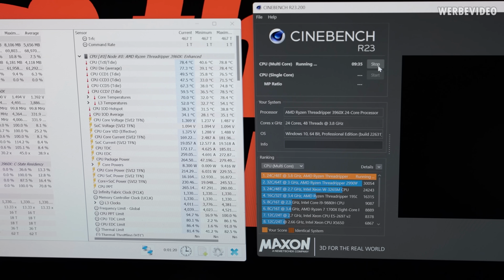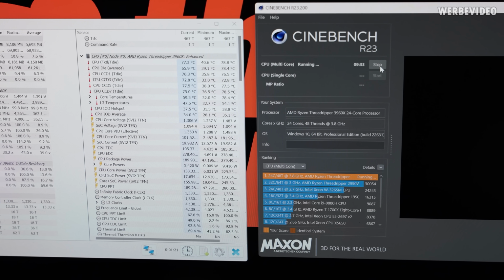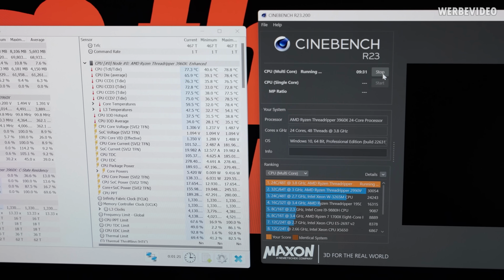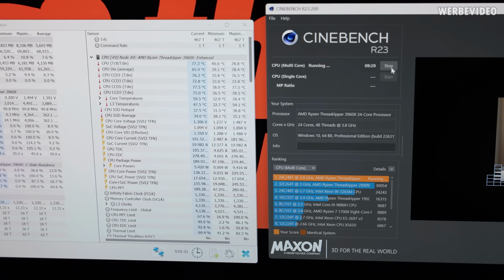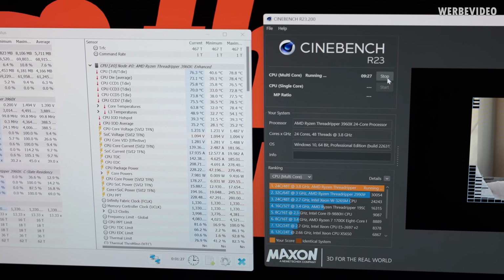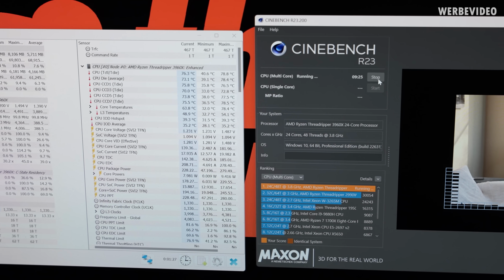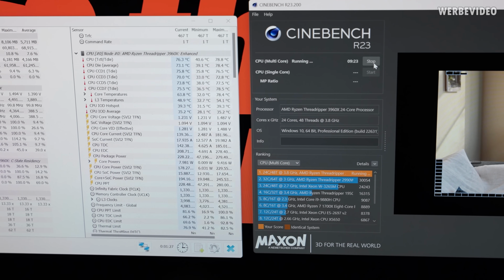Now you can see in Cinebench, the CPU easily consumes about 250 up to 280 watts peak, and still stays below 80 degrees Celsius. And with this, I would basically consider the problem resolved. In total, we had two problems: me being lazy, and the liquid metal eating itself into the IHS, embrittling the IHS over a long time period. I hope it was still interesting for you to see, especially the embrittlement in the surface of the heat spreader.